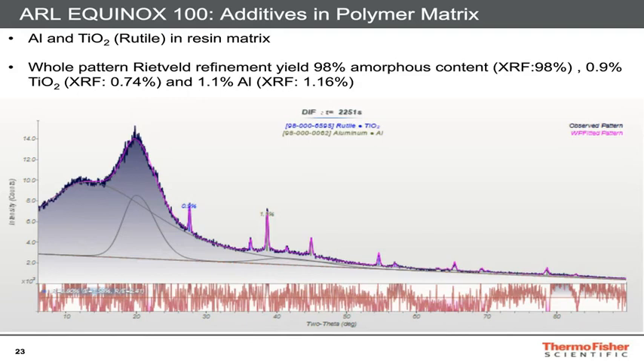In this example, we measured aluminum and titanium dioxide additives in a resin matrix. By means of a whole pattern Rietveld refinement, we can directly refine the amorphous content, which is due to the polymer, and also our solid additives. We cross-check this by X-ray fluorescence spectrometry, and the results are in very good agreement to each other.